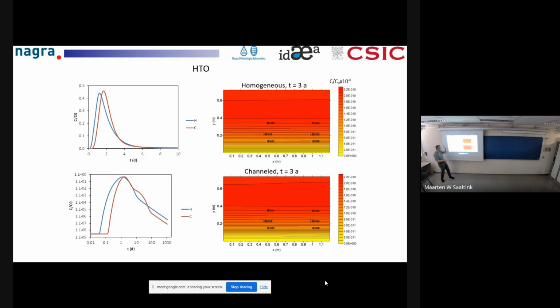And if you look at the typical log plot that we like to use, in the homogeneous case you see the peak, and you have the tail with the typical slope of minus 1.5 characteristic for matrix diffusion. And you look at the channel case, it is more or less the same, and you would have a first tail which corresponds to the fault gouge.